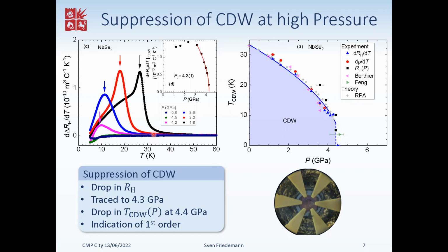Of course. So concerning this sign change in the Hall coefficient, is it that of the inner pockets, so let's say the gamma pockets and the K pockets, one is hole, one is electron, and one gets switched off, or is it that really those which are at the K point are going to change the character from electron to hole? It depends on how detailed you look at the Fermi surface, because if you actually calculate the mass tensor, or the mass tensor element mxy that's relevant for the Hall coefficient, it varies over several of those. Even within one of those barrels, it varies. So one can't say one is just electron-like and one is just hole-like.